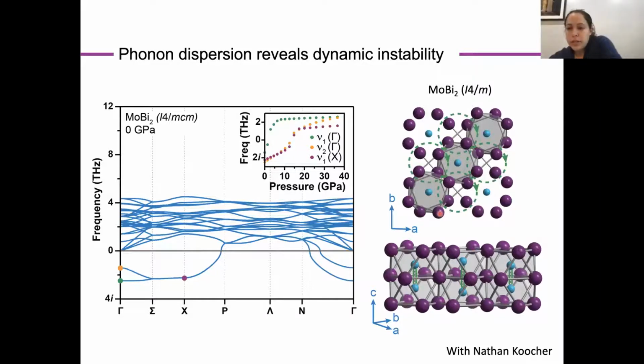Sorry, just to recap. This inset is reflecting the higher symmetry phase, and so we didn't go back the other way, starting from this phase, which is dynamically stable, and increasing pressure. But as I said, I looked at the pressure-dependent thermodynamic properties of this phase as well, and we don't find it on the convex hull at any point in our analysis. I see. Thank you.